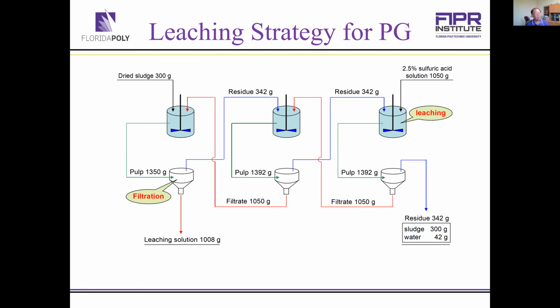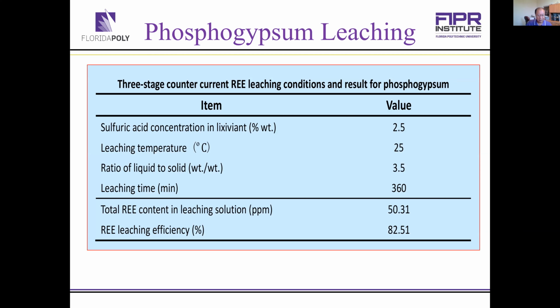For phosphogypsum and the phosphoric acid sludge, we use this counter current leaching process, and also using dilute sulfuric acid to recover the rare earth elements from both gypsum and the phosphoric acid sludge. For phosphogypsum, under these leaching conditions, we got 82% recovery of rare earth elements.